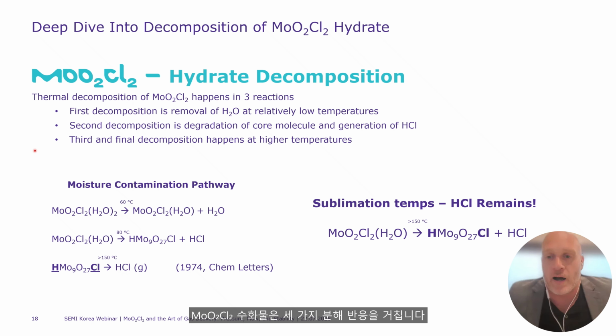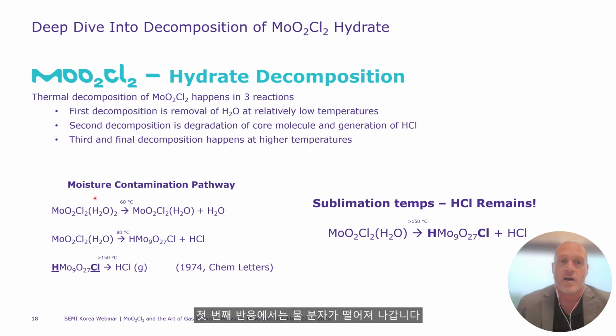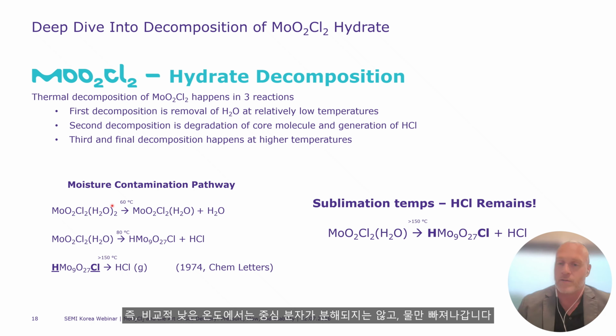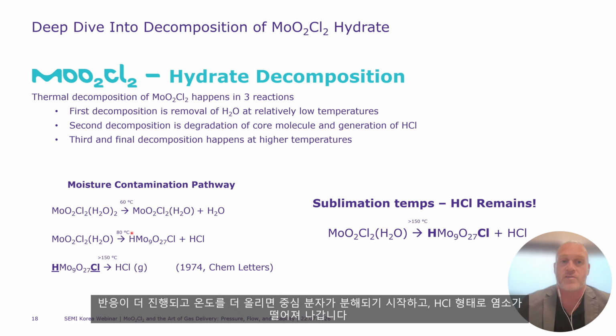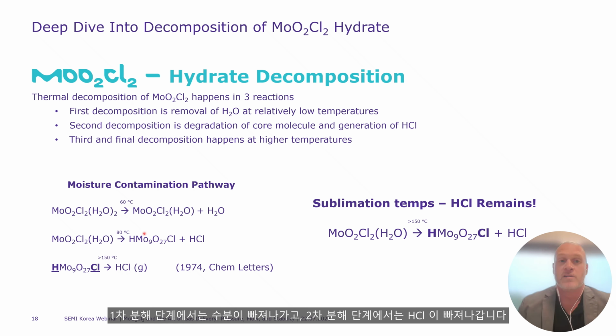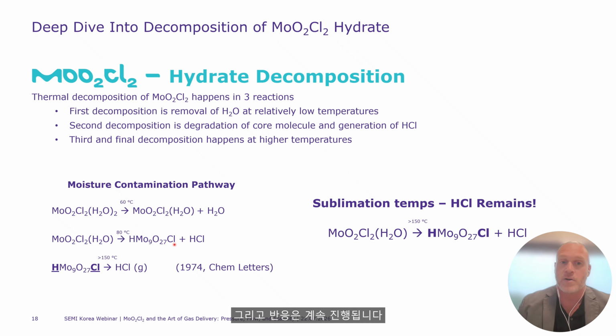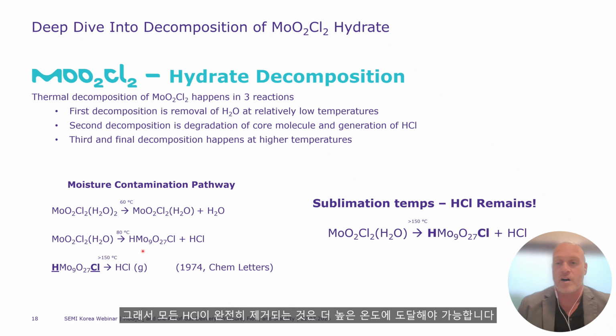So molybdenum dioxydichloride hydrate undergoes three different reactions for decomposition. The first decomposition, shown in this top reaction, is you're losing a water molecule. So at relatively low temperatures, you're not getting core molecule degradation, but you're getting water driven off. As you go down these reaction paths and increase temperature more, you start to degrade the internal molecule and you're kicking off a chloride via an HCl. So the first decomposition, you lose water. The second decomposition, you lose HCl. And you can see here in this middle reaction, there's still HCl tied up in this molecule. It's integrated into the core molecule itself. And so you really don't start driving off all your HCl. You don't get to this final reaction until you're at higher temperatures.